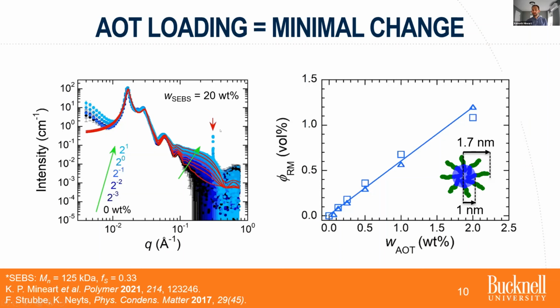I will also mention before I go on, there is a sharp diffraction peak here at about 3 times 10 to the -1 inverse angstroms. And this is actually from crystalline AOT. This is a specific diffraction peak for that phase. And we see it cropping up right at around 1 weight percent AOT. And so all of our experiments moving forward use exactly 1 weight percent AOT because we want to maximize the amount of AOT in our gels while avoiding having any crystalline AOT present.